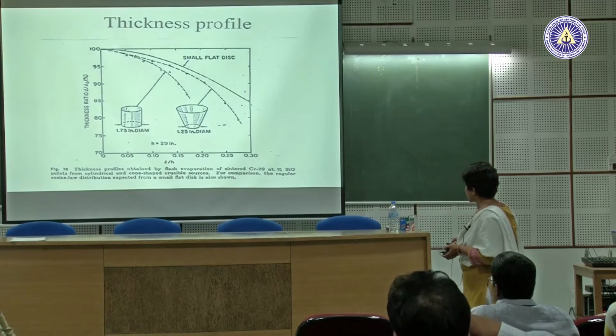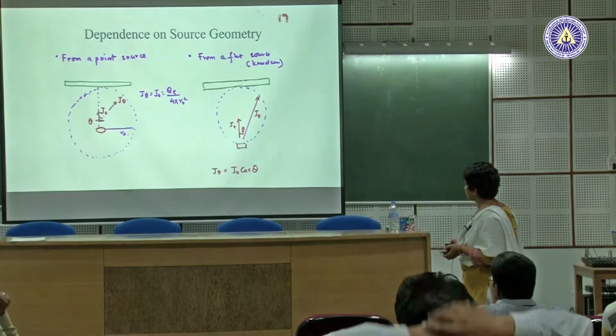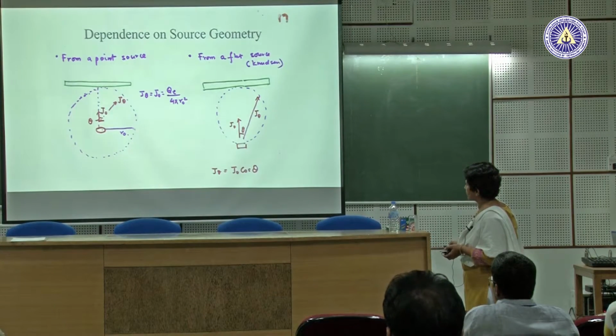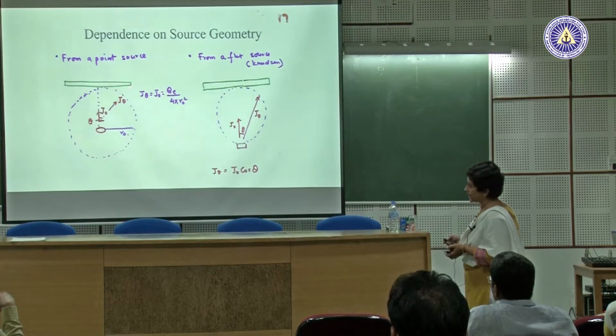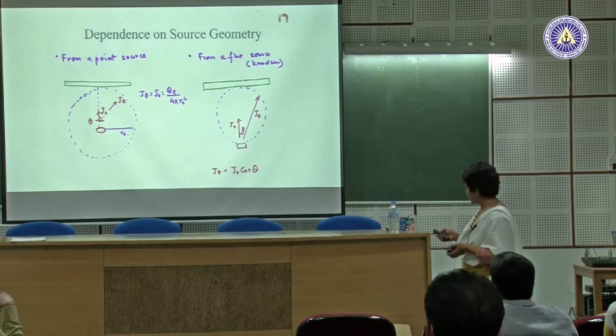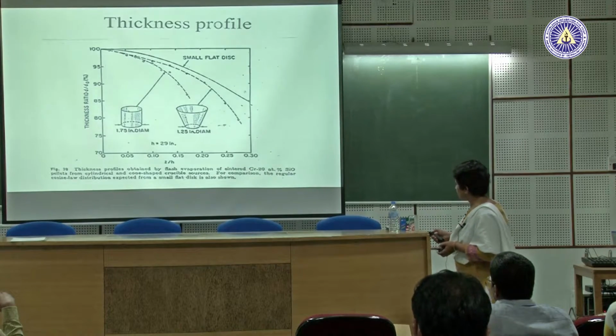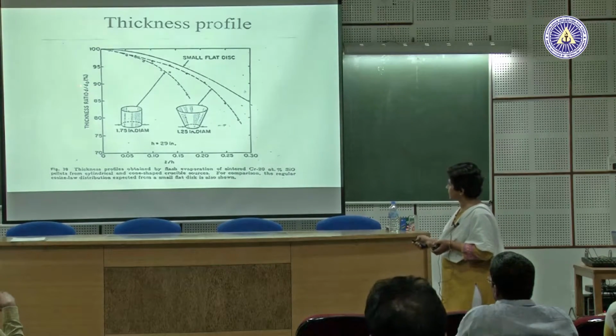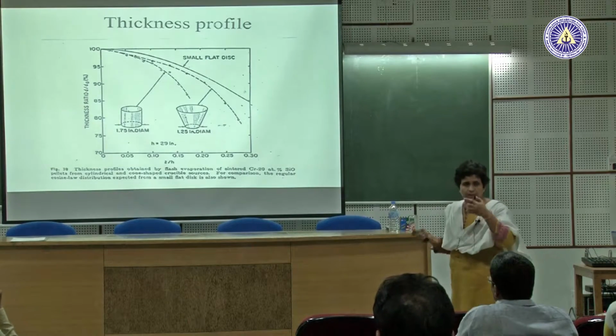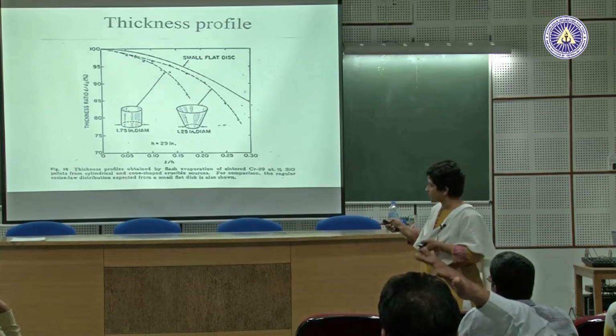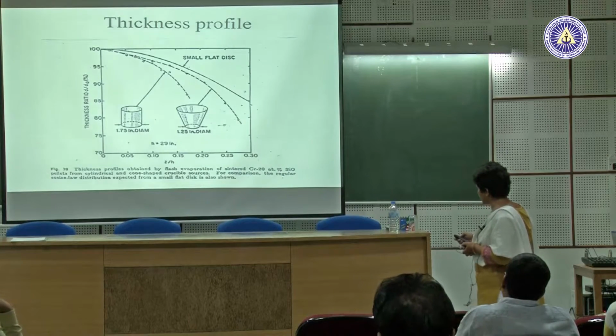So let me go back. If this is the center point, let's say I have the source here, this is the center point, and this distance going away from the center point is divided by the distance from the substrate to the source. If I plot that as a function of the thickness of the film that I am depositing, normalized to what I deposit right at the center, this is the variation you would see if you don't do anything.